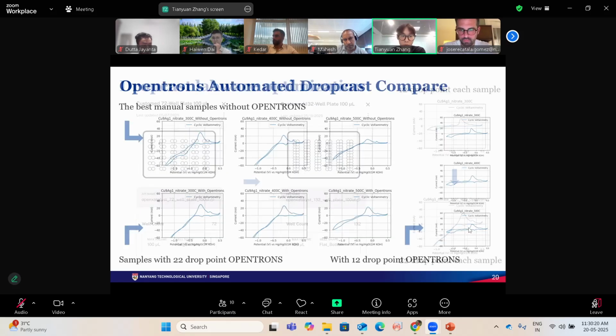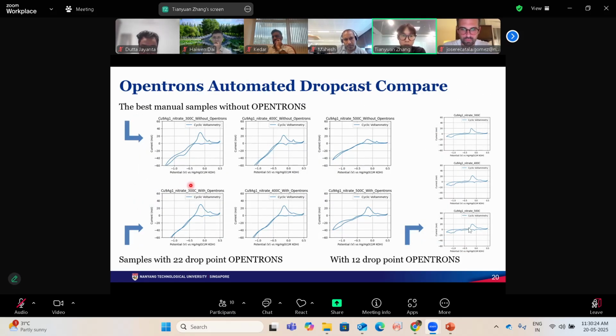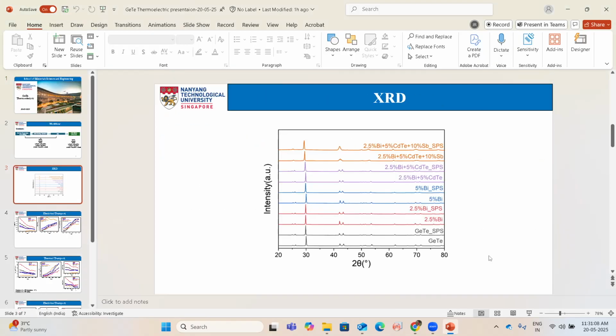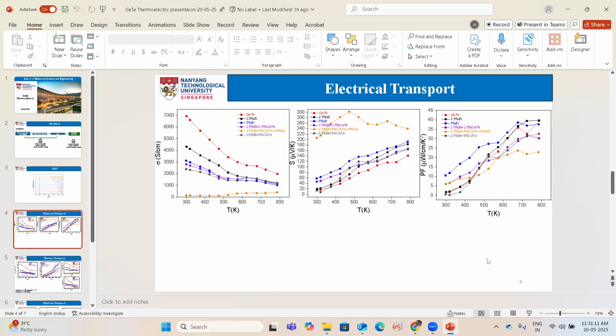And then we start to compare our OpenTrons sample with the best manual samples without OpenTrons, because this batch of manual samples is the best performance that we have ever synthesized. And you can see our new OpenTrons samples even got a slightly higher peak than our best manual dropcast samples. So we believe that OpenTrons samples are promising because there is still some space to optimize later by adding more drop points. And it improved the repeatability of our samples.